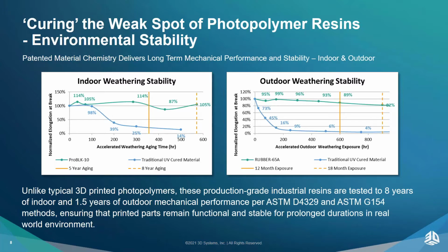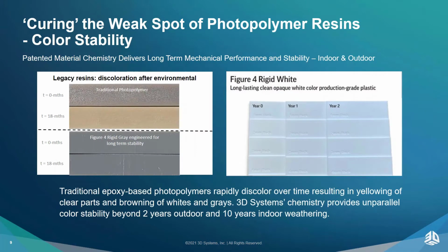The same is true with our Pro Black 10 material, which, when properly stabilized, shows incredible performance over an 8-year period of indoor weathering. Likewise, when we look at an elastomer like Rubber 65A, we see really best in class outdoor and indoor stability. Traditionally, photopolymers, and specifically elastomeric photopolymers, have very poor outdoor performance. We typically see them degrading much faster than the blue traditionally UV cured material we're showing here. But with our novel chemistries and technologies, we're extending the lifetime of these materials well past 1 year of stability and out into 18 months or multiple years.